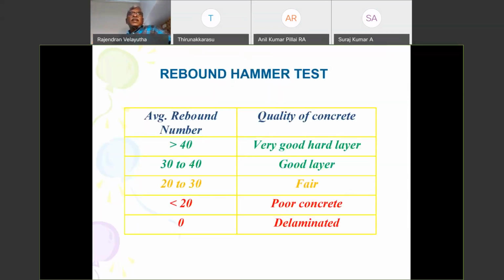Then what inference can we make from this number? If I have a number of 30 to 40, yes, I have a good layer of concrete. But again, this has to be read in combination with your phenolphthalein indicator test, whether the concrete has carbonated or not. If it is already carbonated, doing a rebound hammer on that and then taking a number and going forward with it is not advisable. That's a point which I want to make.